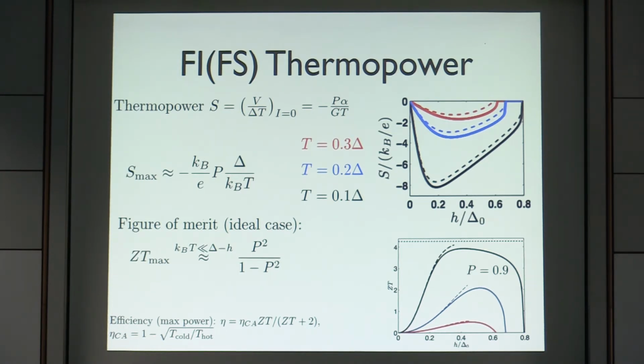You can also calculate the figure of merit in this case. In the ideal case where you forget about all spurious effects such as electron-phonon coupling and so on, which should actually contribute to the heat conductance, this figure of merit at low temperatures depends only on the spin polarization. What you see is that as the spin polarization goes towards 1, this ZT diverges. So you get a very large figure of merit; basically, you should go towards Carnot efficiency.